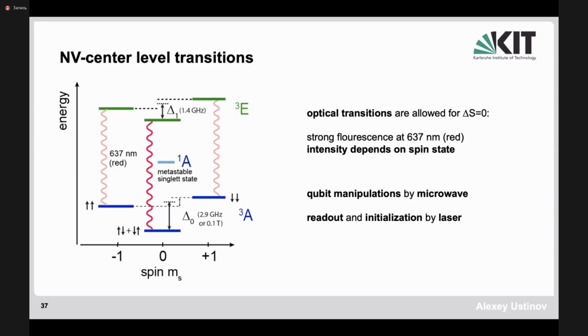Now, when you apply light, optical transitions are allowed for a change of the spin number equal to 0. And there is a strong fluorescence which comes out when we go from the excited states to the ground state, which occurs at 637 nanometers, in the red part of the rainbow, and the intensity depends on the spin state. So there are some intense transitions and less intense transitions.